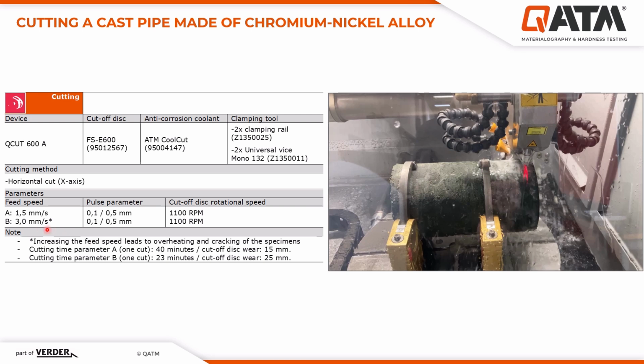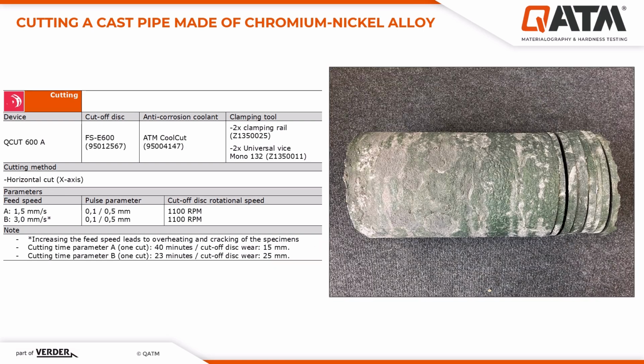But when you use a higher feeding speed, like 3 millimeters, then the cutting time can come down to 23 minutes, but the wear of the cutoff wheel can be 25 millimeters. And then we can decide which of them is more important for us: the time, the wear of the cutoff wheel, or the quality of the cut.